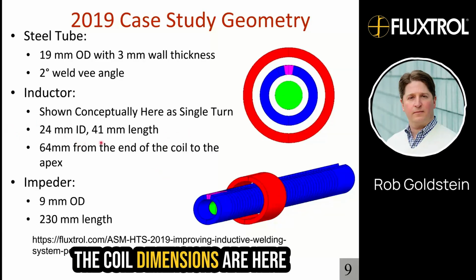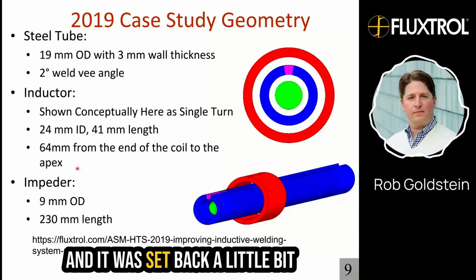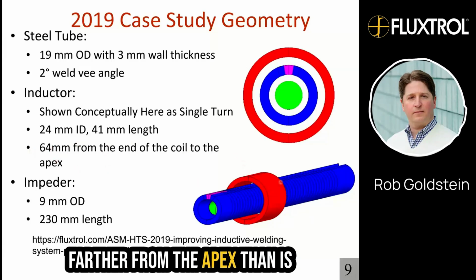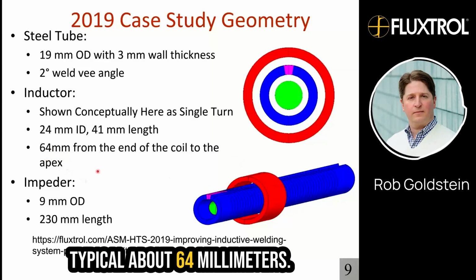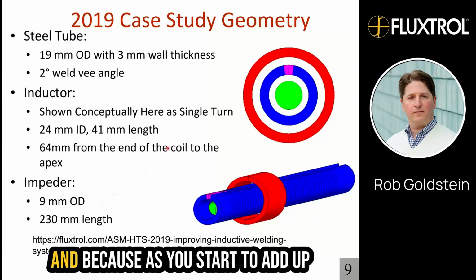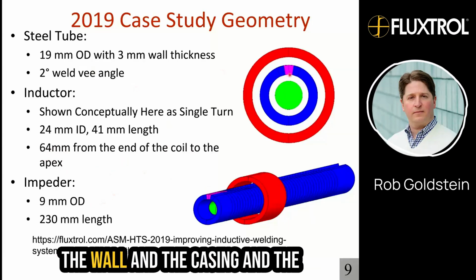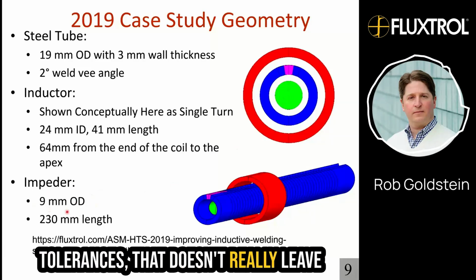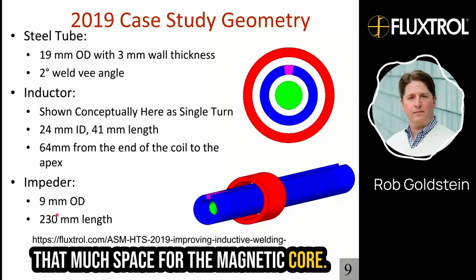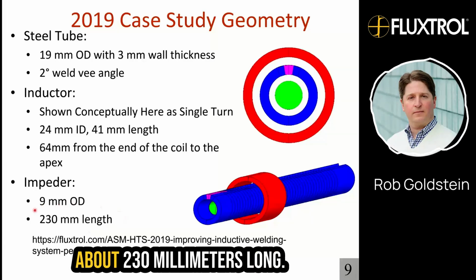The coil dimensions are here, and it was set back a little bit farther from the apex than is typical, about 64 millimeters. Because as you start to add up the wall and the casing and the tolerances, that doesn't really leave that much space for the magnetic core. And the magnetic core was about 230 millimeters long.